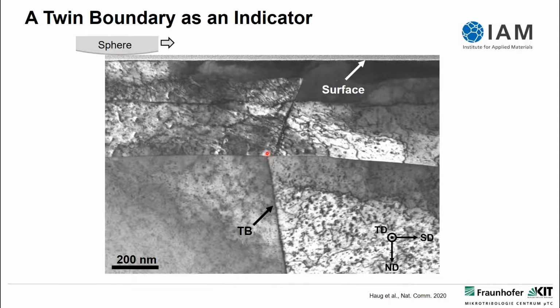We know that for all intents and purposes, when we cut also beside the wear track, we can prove that this twin boundary, before tribological loading, was going up like this. Those annealing twins are really sharp, line-like structures. So we know that before the tribological load, this line would just extend here towards the surface. But no more, after the tribological load.